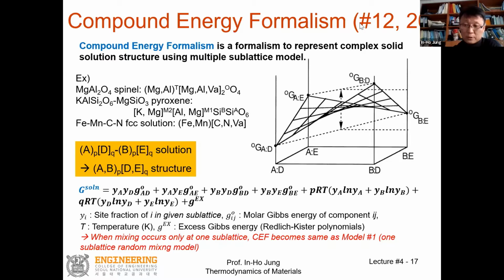One of the big differences of the quasi-chemical solution is that the entropy of the quasi-chemical solution model changes automatically with the interaction parameter between A and B. So the bonding energy in the solution can change the entropy. That was the advantage of the quasi-chemical model, but it makes a really big complexity in the entropy term. But anyway, that's a big advantage.